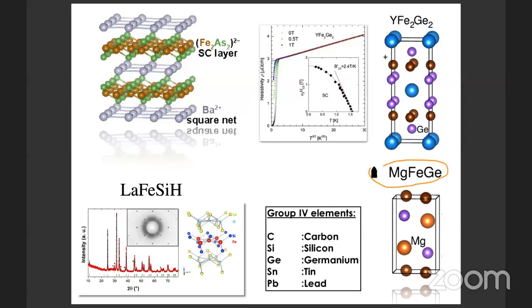Thus the magnesium iron germanium compound was found to be isostructural and isoelectronic with the lithium iron arsenic compound, but displaying no superconductivity. So this compound is probably more strongly correlated than the lithium iron arsenic sample, since it has a large magnetic moment compared to lithium iron arsenic. By the same argument, it is probably less correlated than the iron selenide compound. And thus correlation effects are unlikely to be responsible for the absence of superconductivity in these systems.